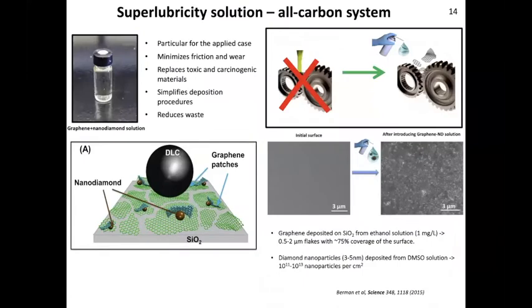With that, we created this new so-called superlubricity solution. If initially in our solution we had only graphene, now we added diamond nanoparticles to the solution. You can see this is a schematic of how our system looks. There are some graphene flakes, and then there are some diamond nanoparticles around 3 to 5 nanometers in diameter. They are explosion-based, round-shaped diamond nanoparticles. Whenever we drop cast or spray coat this solution on the surfaces, you can see this coverage. I hope that you can see some contrast in the image.